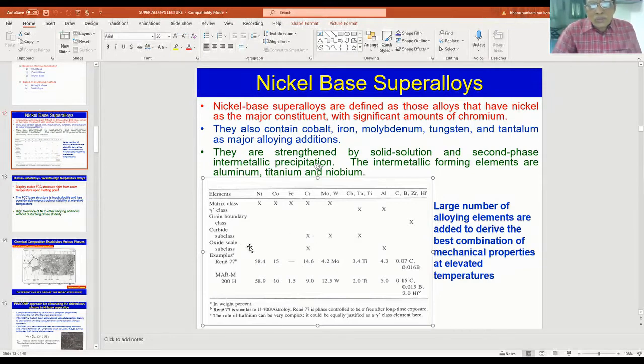Oxide scale class: chromium and aluminum. Aluminum is the element which contributes to major strengthening in the material in the form of gamma prime phase, but at the same time, aluminum also forms alumina, and that contributes to oxidation resistance of the alloy. Now there are some elements which will go only to grain boundaries: carbon, boron, zirconium, and hafnium. They contribute to grain boundary strengthening.